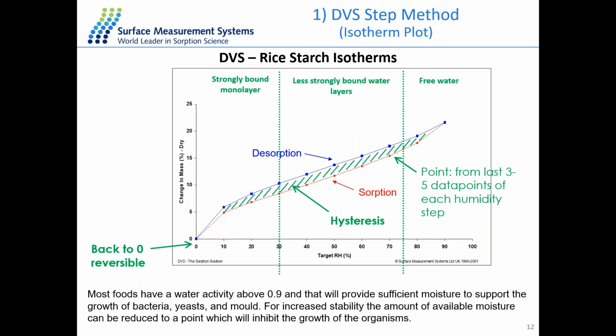So isotherm is a very important parameter to interpret the moisture sorption mechanism from the shape of the isotherm. Some information you can get from this isotherm plot, for example, at 90% RH, the sample can pick up about 20% change in the mass. That means the rice starch sample has a very good affinity with water. And those water molecules are not just on the surface, but also go to the bulk of the material. So it's a bulk sorption dominated mechanism.